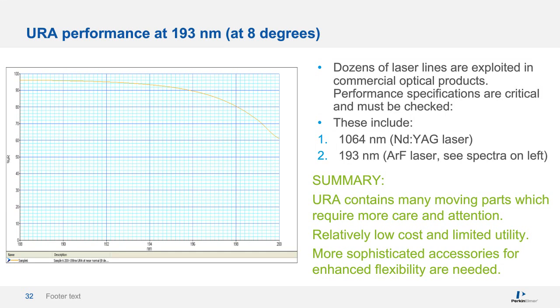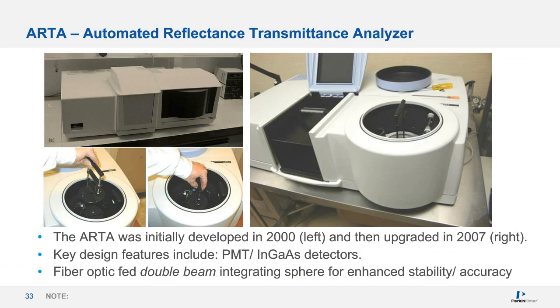The Automated Reflectance Transmittance Accessory, or analyzer, is generally considered to be the first goniometer-based accessory that was available commercially. It was developed around 2000 for the Lambda 900 and was then optimized and upgraded around 2007 for Lambda 950. As will become clear, the sample is inserted into the center of the accessory such that the sample and detector can move independently to generate specular as well as off-angle measurements.